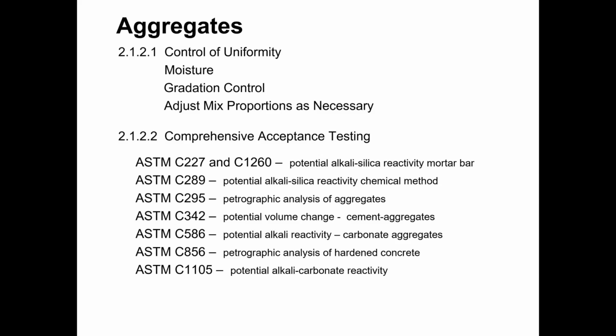Others are short-term tests that may be able to be done over a period of a few weeks. So oftentimes what a plant will do is they will do the short-term tests so that they get a pretty quick result. If that result indicates that there are no issues with reactivity or what other factor was being evaluated, then we say that the aggregate is acceptable for use and we move on. If the short-term test, which tends to be less accurate than the long-term test, indicates that there is a potential issue with reactivity or some other parameter, then we may go ahead and do a long-term test as well, just so that we have better information with regard to just what level of reactivity that aggregate is actually at.